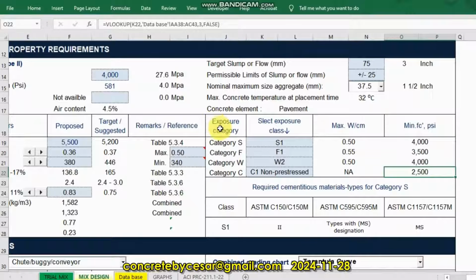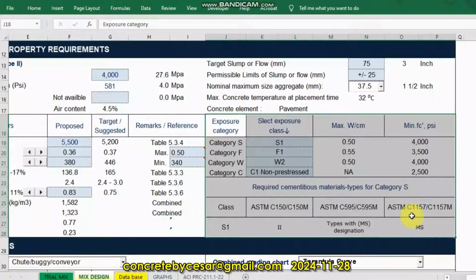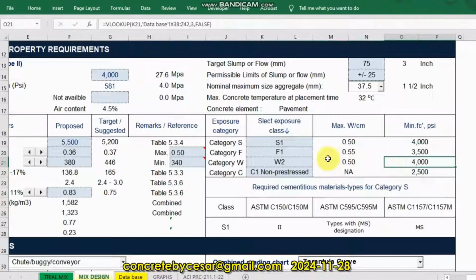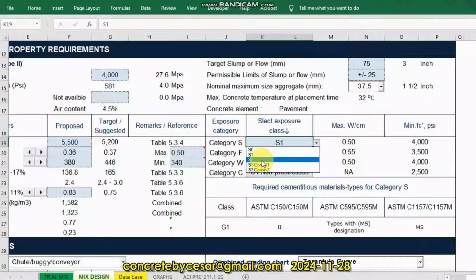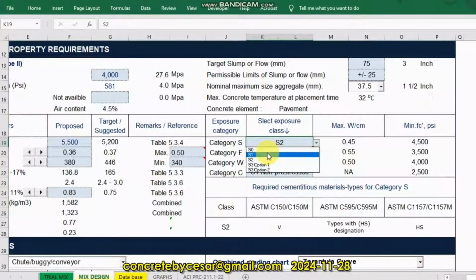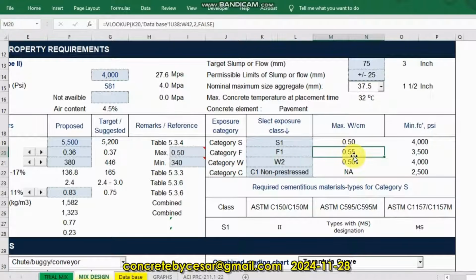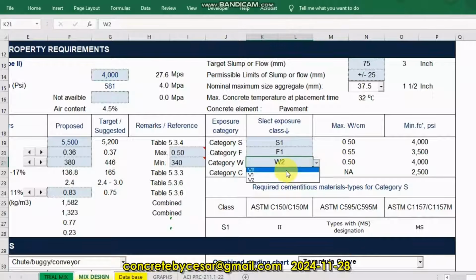Next, we'll go below here. If you have a specification like in US regarding the exposure category, then this area will be helpful for you. Here you just have to select according to your specification again. Let's say, for example, category S2, so automatically it will appear the suggested water cement ratio or recommended maximum water cement ratio and the minimum strength. So let's go back to S1 in this example. Remember that I used F1, that's why I selected here also F1 for the category F. Water cement ratio maximum 0.55 with minimum strength of 3,500 psi, and so on for category W and category C. So you just have to select according to specification.